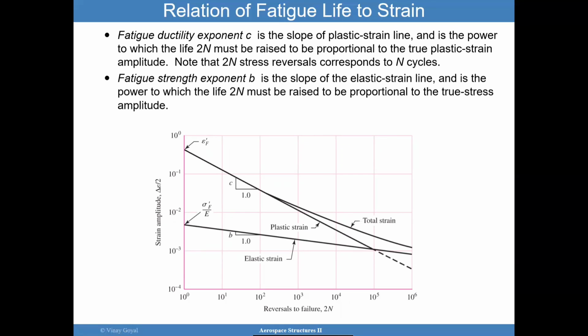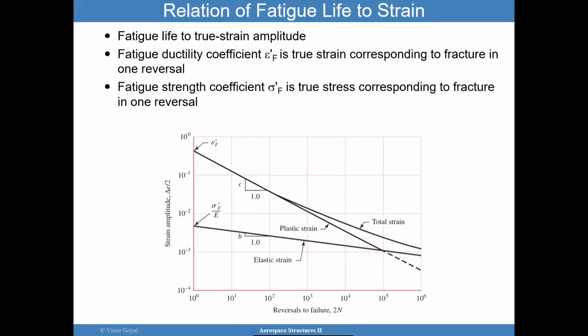You also have the fatigue ductility exponent is the slope of the plastic strain line. And you have the fatigue strength exponent is the slope of the elastic strain line. And again, so you have this exponent and then you have this exponent. This one is for the plastic portion, this is for the elastic portion. And these two fatigue exponents really drive the behavior of the strain to failure calculations.